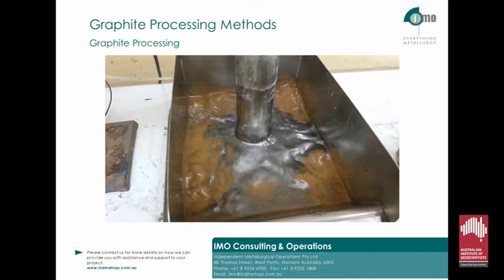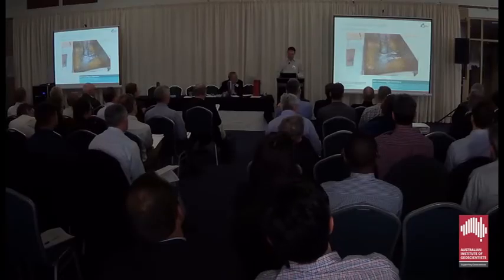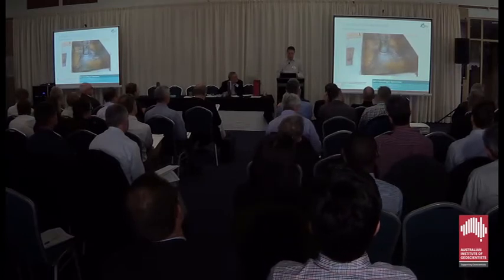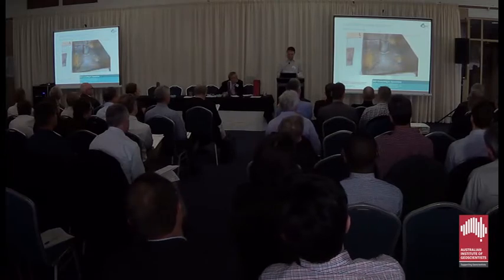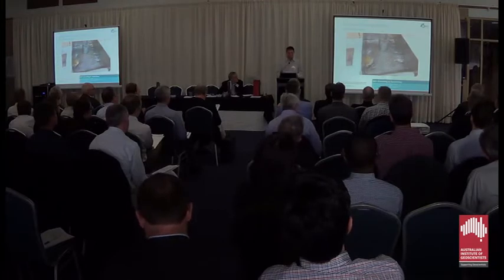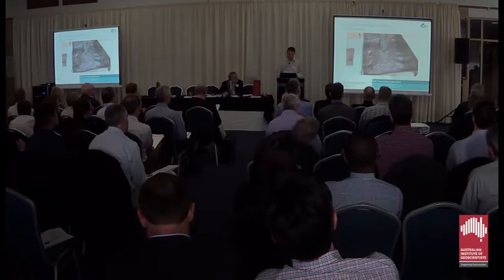The video commences at the end of the conditioning stage, which generally ranges from 2 to 5 minutes, and you can see there is more graphite on the surface of the slurry. As we slowly add air, the graphite begins to form a froth bed, which continues to rise to the top of the cell as the airflow rate is increased. If you look carefully within the froth, you'll see fine gangue, which is physically entrained within the froth and ultimately needs to be removed during further cleaning.